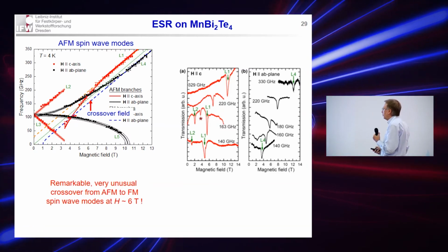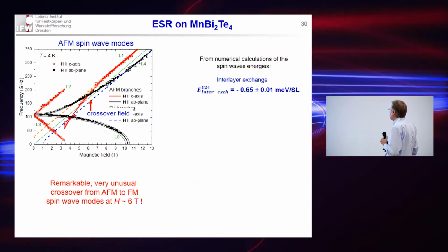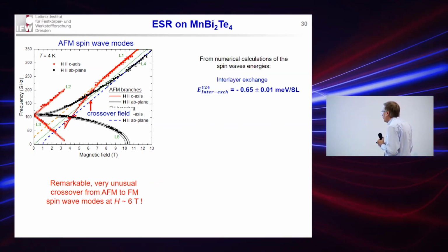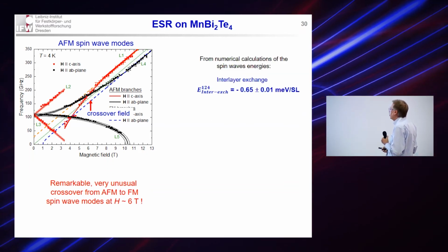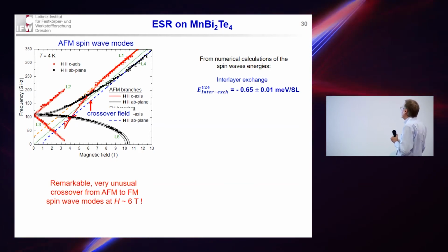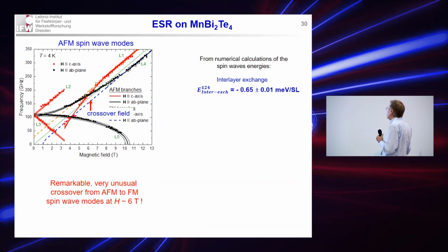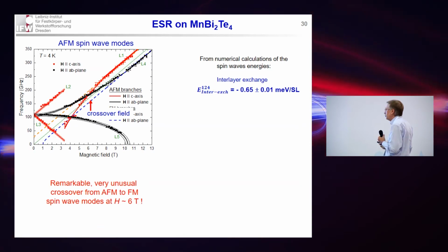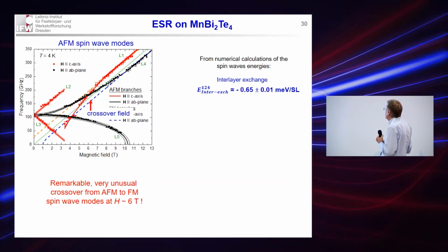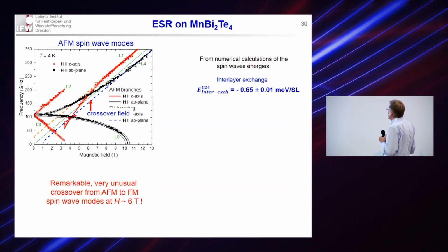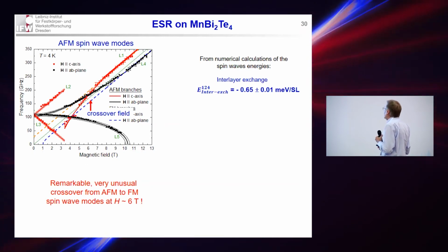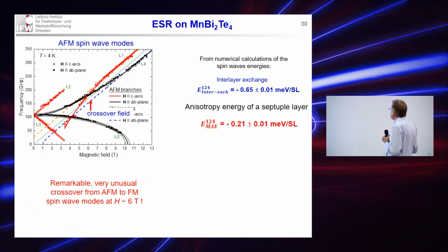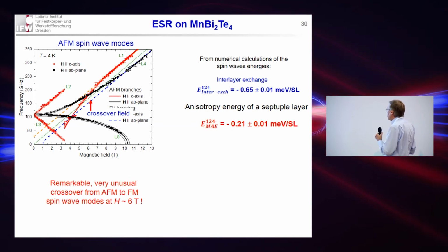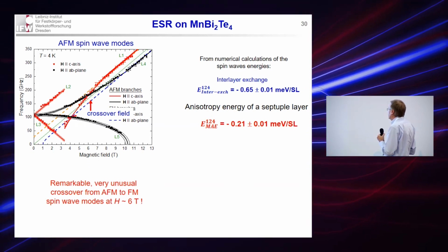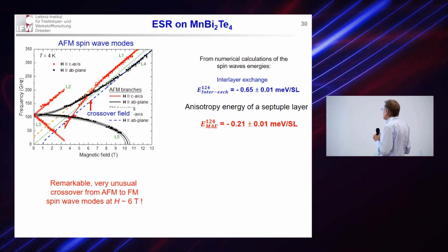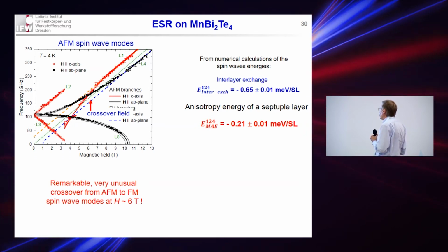So now, what is the physical consequence, or the physically relevant conclusion from this observation? We could fit all of these antiferromagnetic modes again with the spin wave theory, and we could obtain the exchange interaction between the layers, between these magnetic units. It's also negative, antiferromagnetic, about 0.7 milli-electron volts. And we also obtain the anisotropy energy of an individual magnetic unit, the septuple layers. It turns out to be negative, minus 0.2 milli-electron volts.